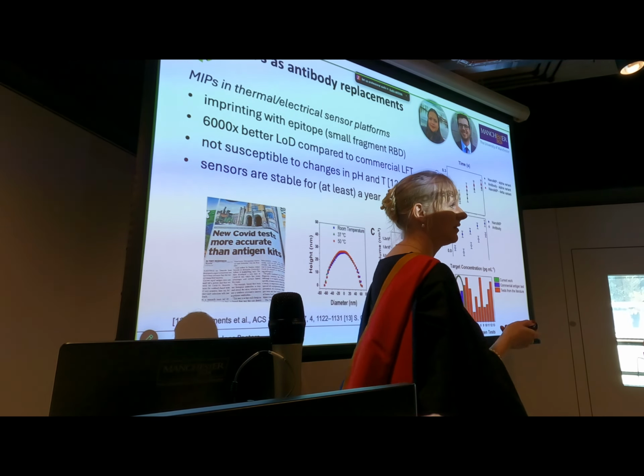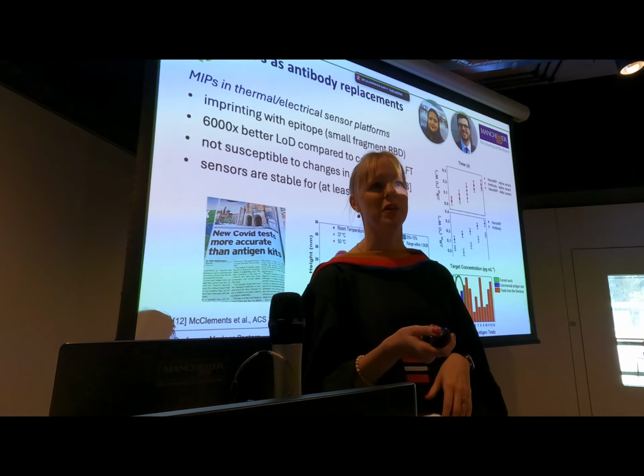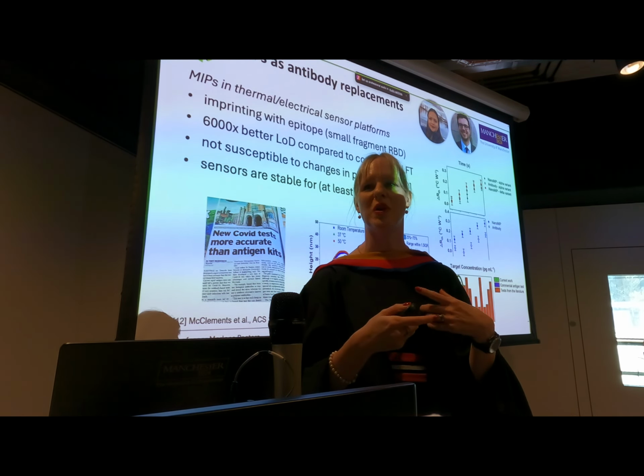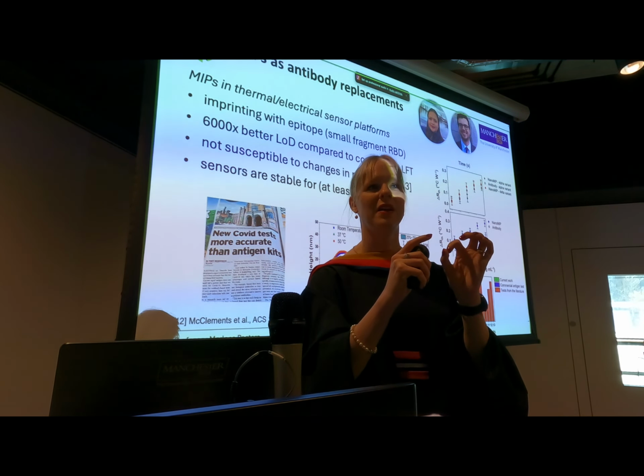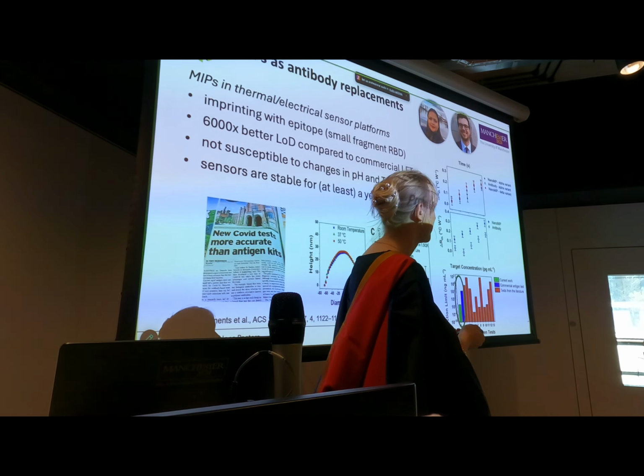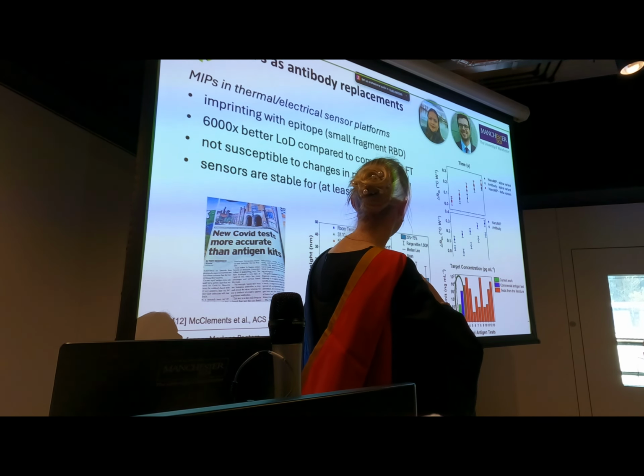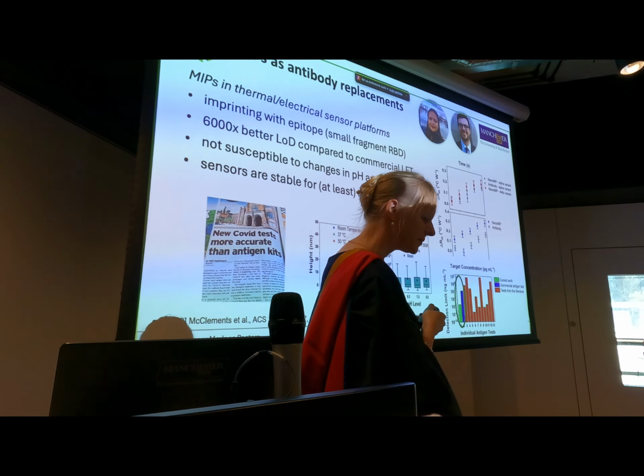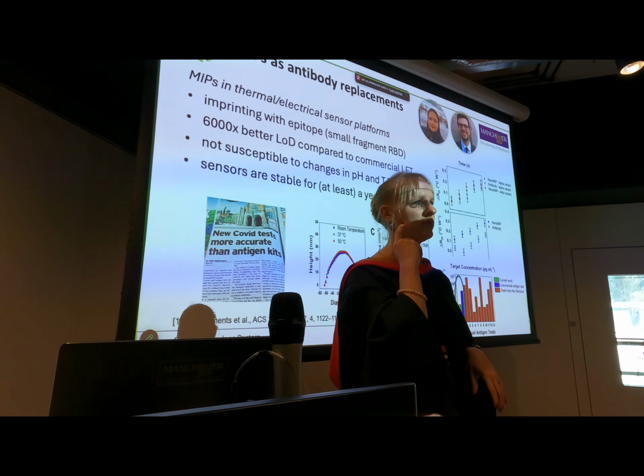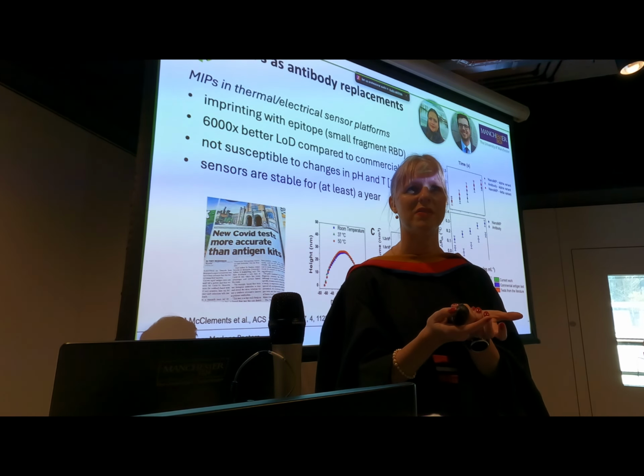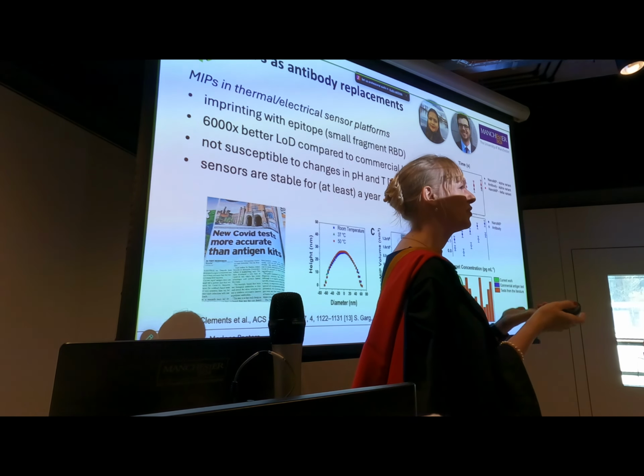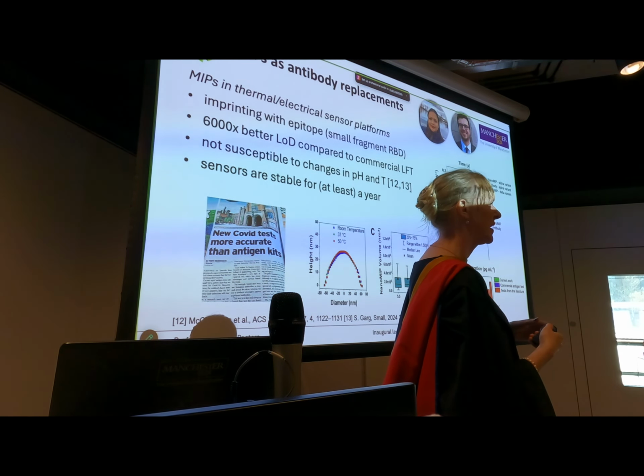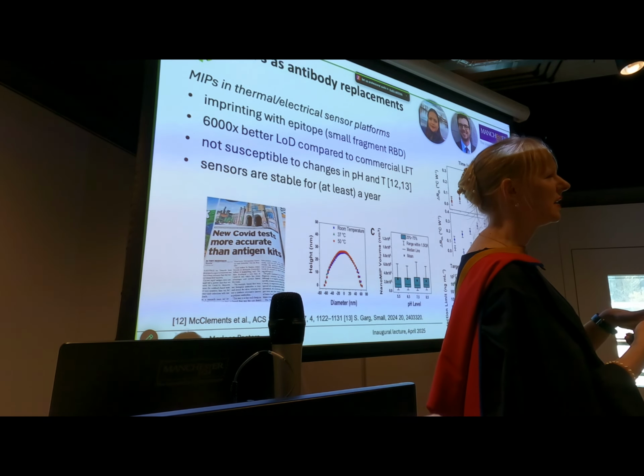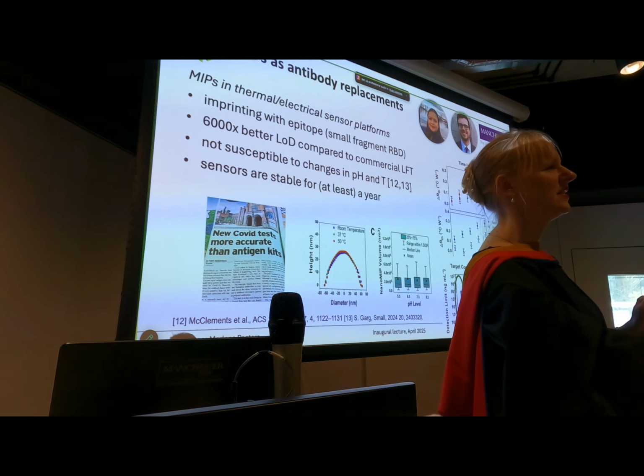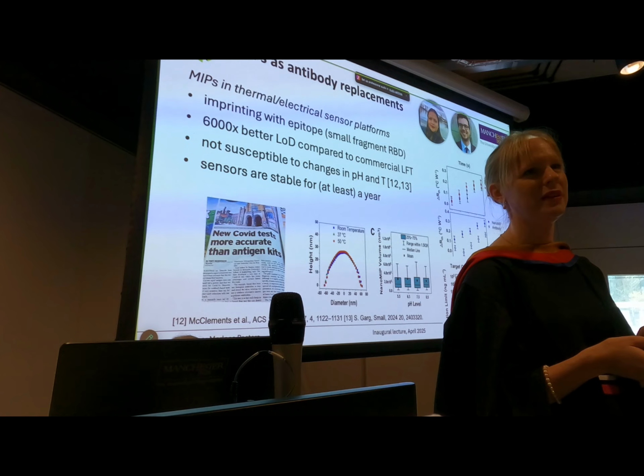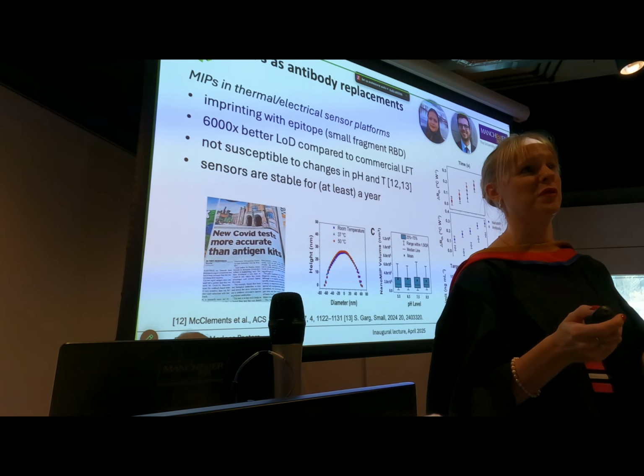And we also know that there are, especially in COVID-19, a lot of mutants. So you need to make sure that whatever you're picking can also detect whatever is coming after this. So this was a small fragment from this receptor binding domain. And what we actually found out, if you compare it to your lateral flow tests, you might have noticed that it was missing cases, especially when you would start to feel a little bit unwell, and a few days later, suddenly you would see this positive line. So actually, the lateral flow tests are not very good.